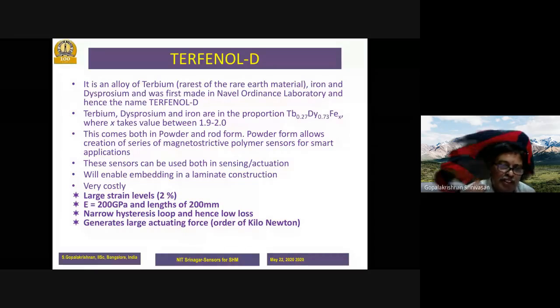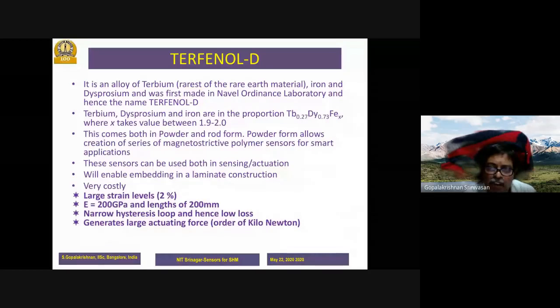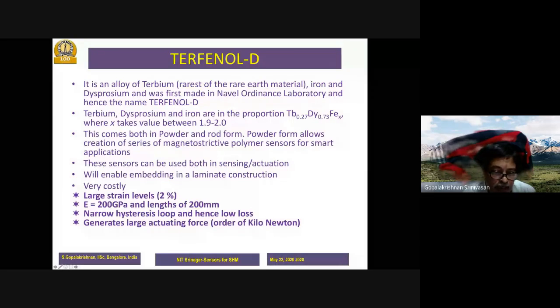So initially, when this material was made in the Naval Ordnance Lab, it was thought of as an actuation material. It has a narrow hysteresis loop compared to piezoelectric material, hence the loss is very low. However, it is heavy. It has stiffness as high as steel, 200 GPa, and it can come in lengths of 200 millimeters.